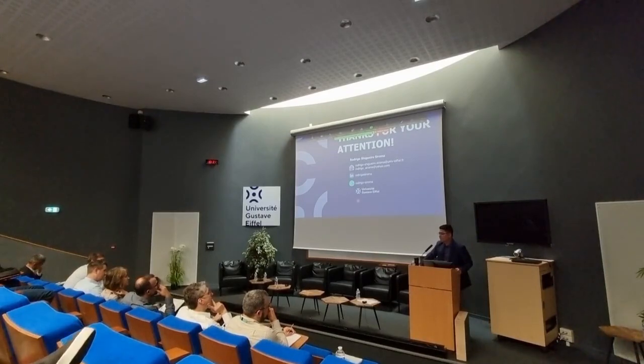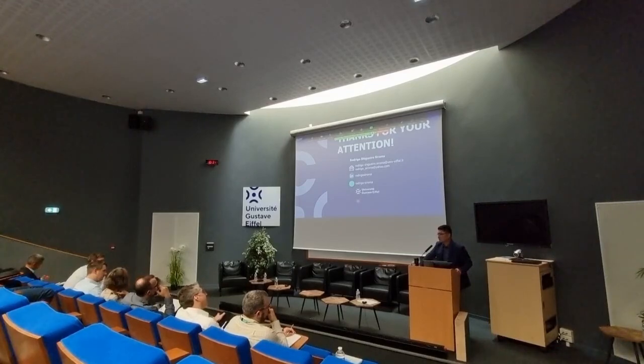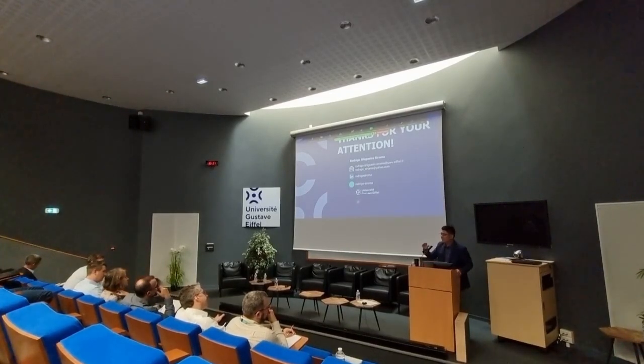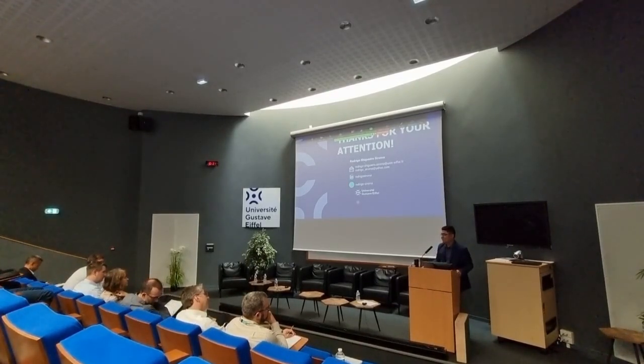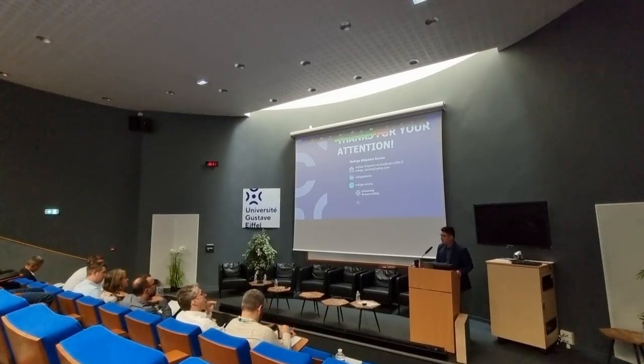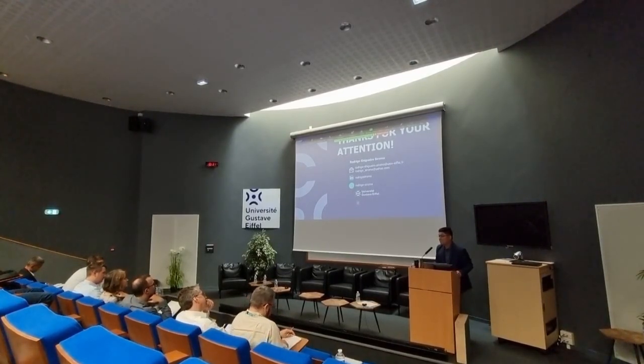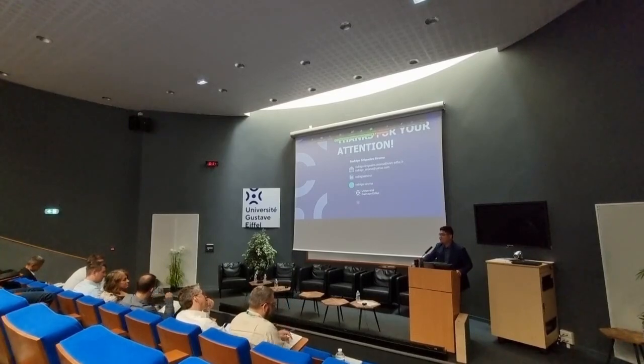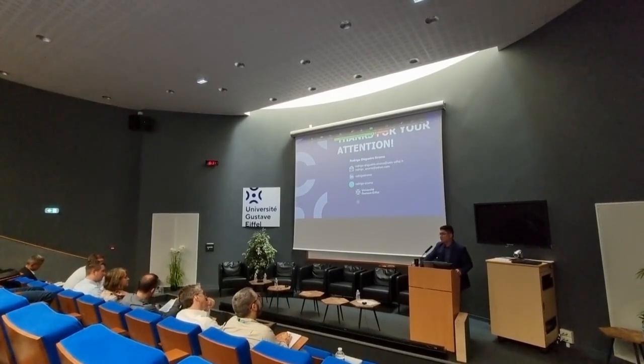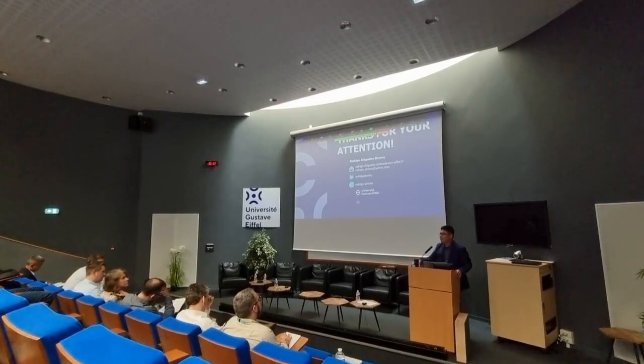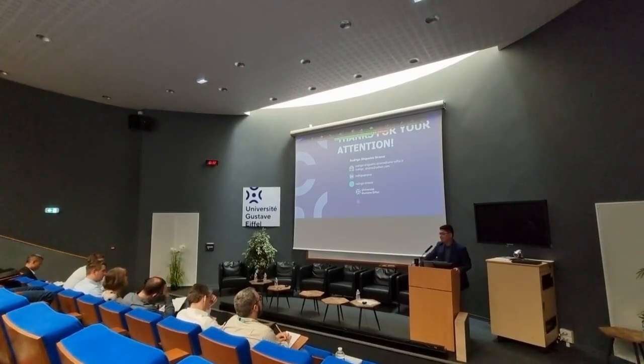Because with fatigue and, well, many modulus tests, which were done here at Université Gustave Eiffel, we observed this increase in modulus that we just don't understand how this increased value could be used, for example, to estimate the remaining service life. which is why we started looking at other tests to see if this would also validate or correspond to the performance level of our already aged material.